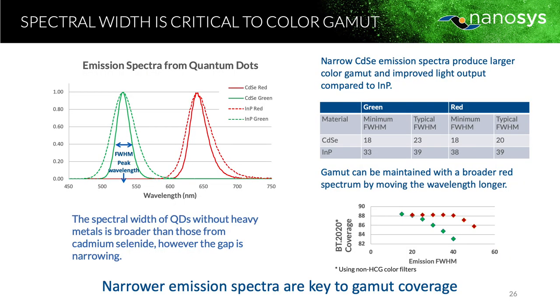Another thing that's important to color is spectral width. And I'm going to talk about two different materials here, cadmium selenide-based quantum dots and indium phosphide, or also people refer to them as cad-free quantum dots. And I mentioned that the BT 2020 standard was to have monochromatic sources of light. Well, this is not monochromatic by any stretch of the imagination, but they're pretty narrow emission spectra compared to most other emitters. Both of them are, actually. And so you can see that the cadmium selenide system is still narrower than the corresponding indium phosphide quantum dots. But I will say that's changed a lot over recent years. The indium phosphide used to be much broader, and so the technology is really improving for these. And they're both very good emitters.